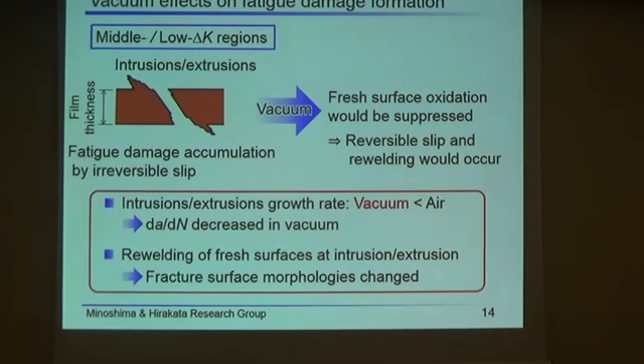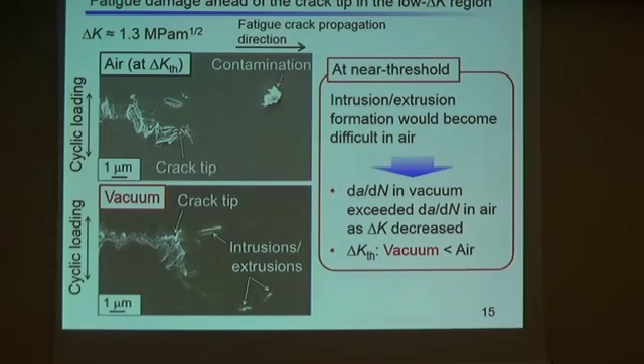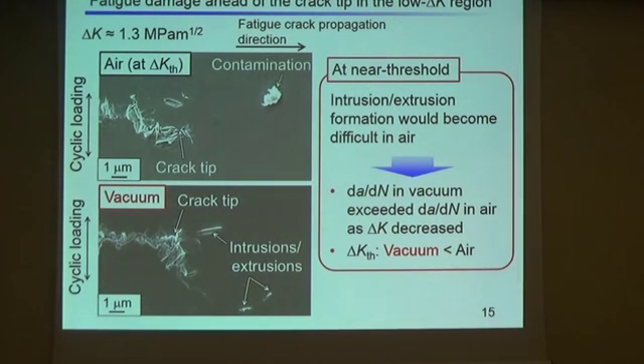However, the vacuum effects in the low delta K regions cannot be explained only by these factors. So, to investigate the vacuum effects in the low delta K regions, fatigue damage ahead of the crack tip in near threshold regions was observed. This is the crack tip in air and vacuum.